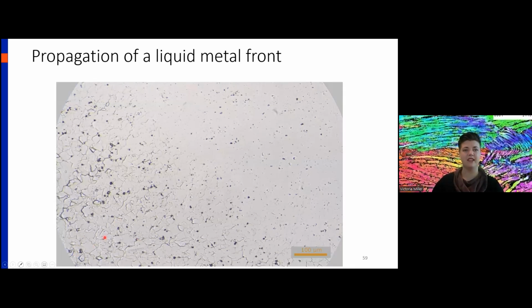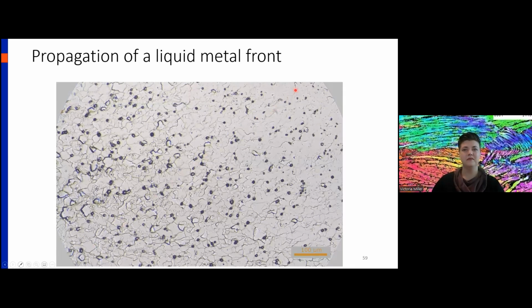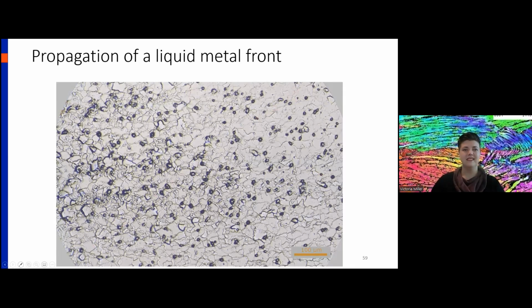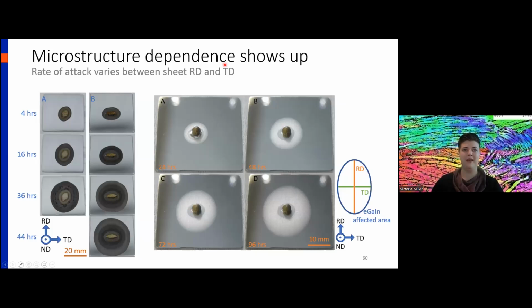Here it is at slightly higher magnification. And you can start to see that microstructure dependence of this rate of attack shows up, both for oxidation and for the grain boundary wetting mechanism. So if you look at the rolling direction, which is vertical here, and the transverse direction, which is horizontal, you can see that in each of these cases, you get propagation faster along the rolling direction than you do along the transverse direction. You get a very slightly different rate of attack.